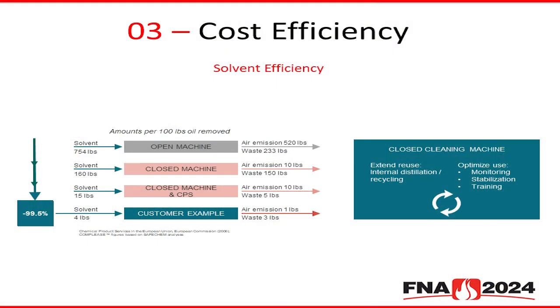If you close that technology, then you can already reduce that significantly down to 10 pounds per 100 pounds of oil. And if you then apply what we call chemical product services, CPS, like monitoring tools to test the solvent, stabilize the solvent to bring it back to the virgin quality again, then you can reuse the solvent in the machine again and again and further reduce the consumption to only 15 pounds per 100 pounds of oil being removed. So that's an official case study available from the European Union.